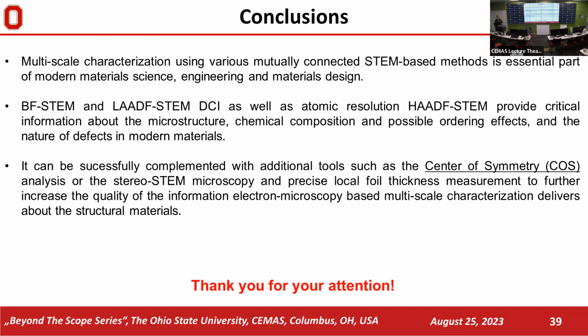If you do a normal scan using normal settings, you orient your crystal, you have your place, and you just set up the scan with reasonable resolution, but it's not atomic resolution on a random sample. The sample is not specifically prepared for atomic resolution EDS. Then you'll not see it.